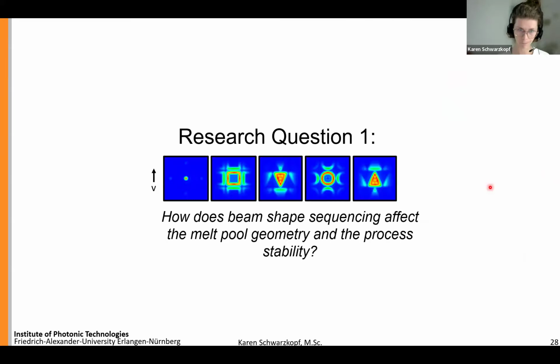Now let's jump into the first findings, which are dealing with the melt pool geometry and the process stability. Here you can see the in-situ video of the melt pool geometry, and on the right, the resulting top view of the weld seam. As you can see directly from the video, when changing beam shape, we also do see differences in our weld topology. We can really see the differences of the beam shapes already in our melt pool. One thing that also has to be mentioned here is that these changes occur in a repetitive way, meaning that the dynamic beam shaping approach is really leading to a repetitive material response.